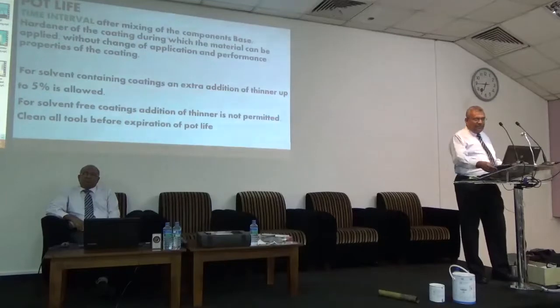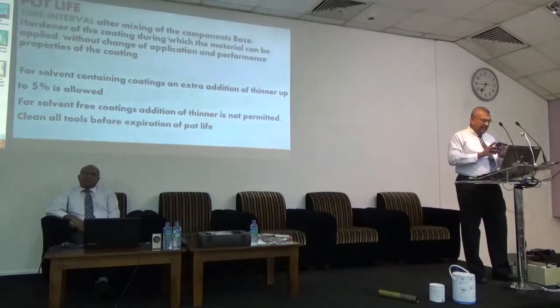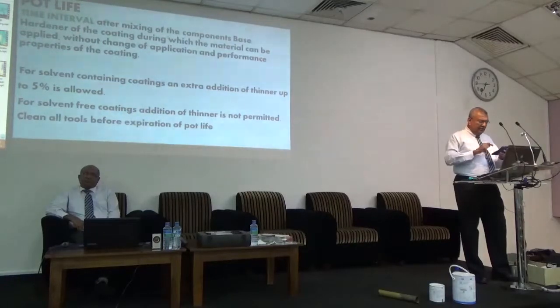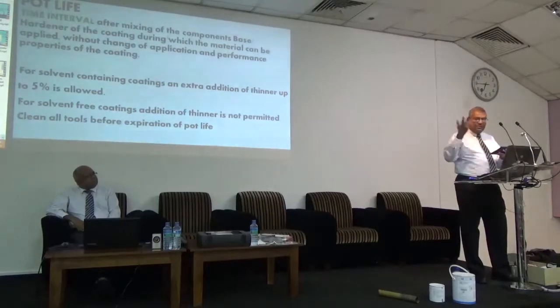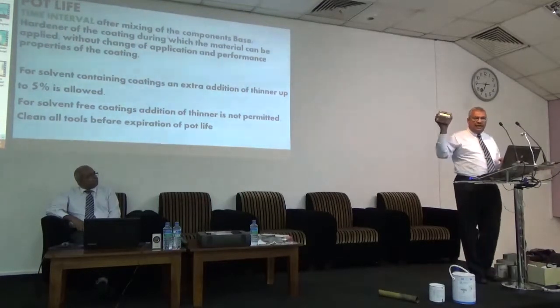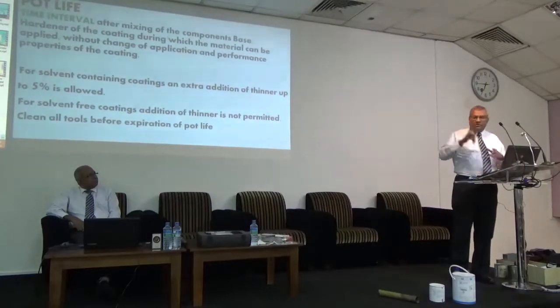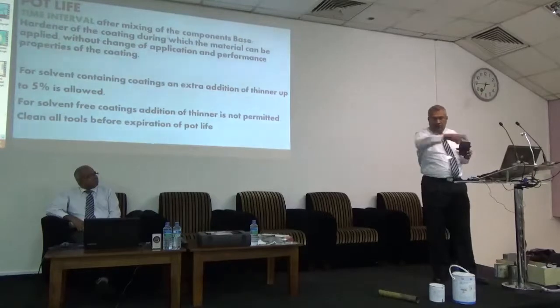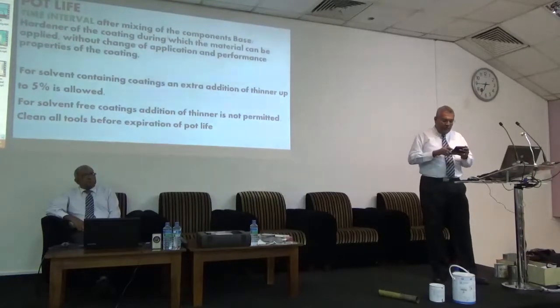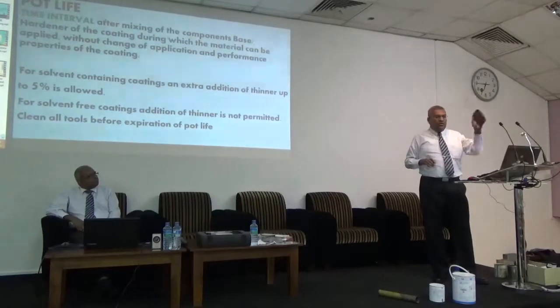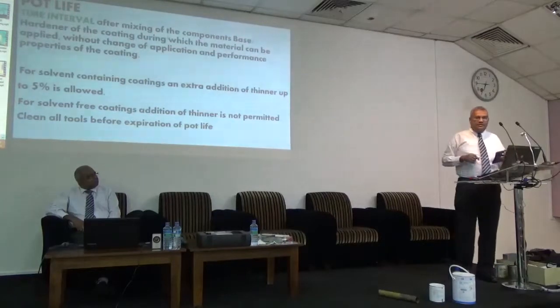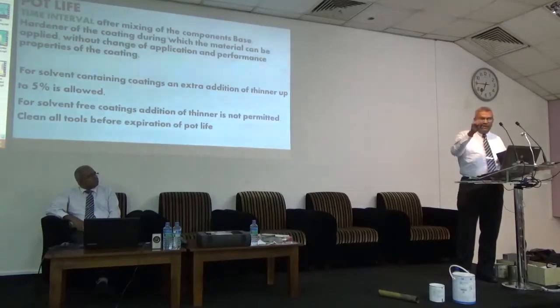So you have this formula. The solid content is 57 into 10 over 75 microns. It is 7.6 square meter per liter. So you multiply by 0.7, 30% loss factor. So you know with 1 liter, 5.32 square meters you can apply. So you take a measurement and say, okay, we have 5.32 into 4 liters. 21 square meters you can apply with this paint at 75 microns.